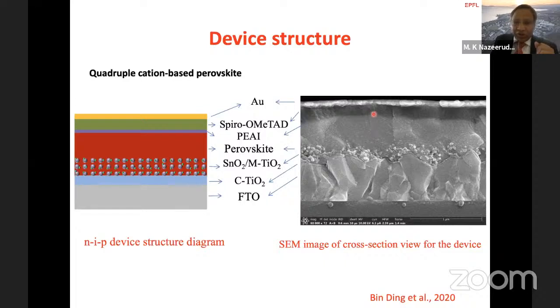This is perovskite. The compositional engineering of this perovskite is very important for the crystallinity of these materials. Now, if you look at these crystals, they are blocks contacting the ETL layer, that's TiO2. On the top, we have a hole transporting material, on top of the perovskite, followed by a contact. So this is the configuration. Such a simple configuration gives you 25% efficiency of the perovskite solar cells.